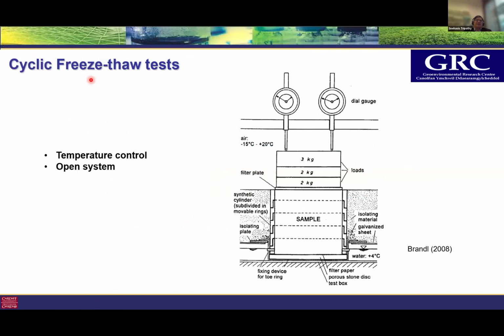Here is a cyclic freeze-thaw test. Frozen boundary conditions can be imposed by controlling temperature at one end of the sample. Of course, this time it's negative temperature. So we need to take the temperature down below 0 degrees centigrade to freeze the sample or to create the frozen condition. This can be achieved by circulating cold air or oil at desired temperatures in a non-contact mode. Also, some researchers have used a metal plate whose temperature has been lowered to any desired temperature.